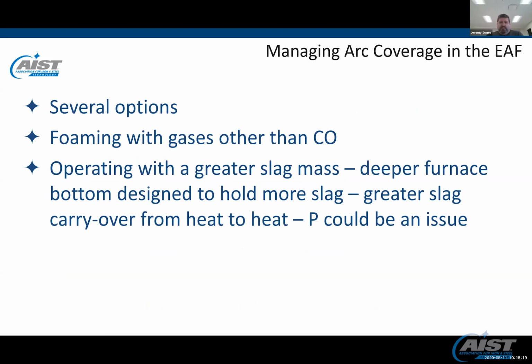The other options for managing arc coverage, we've got several. We can foam with gases other than CO. We could operate with more slag mass and design the furnace to carry over a greater amount of slag, because it doesn't matter how we bury the arc, just that we bury the arc. Of course, a larger slag mass would be a slightly greater heat sink, but it could be manageable. Of course, if you're working with some materials that contain a lot of phosphorus, then it becomes an issue, because you have to flush the slag in order to get the phosphorus out of the steel and out of the system.